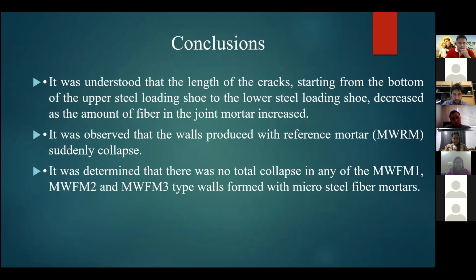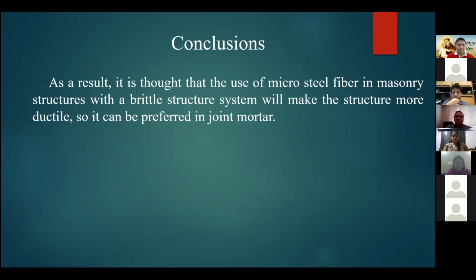It was understood that the length of the cracks from the bottom of the upper steel loading shoe to the lower steel loading shoe decreased as the amount of fiber increased. It was determined that there was no total collapse in any of the MWFM1, 2 and 3 types formed with microsteel fiber mortars. As a result, it is thought that the use of microsteel fiber in masonry structures with a brittle structure system will make the structure more ductile, so it can be appropriate in joint mortar.